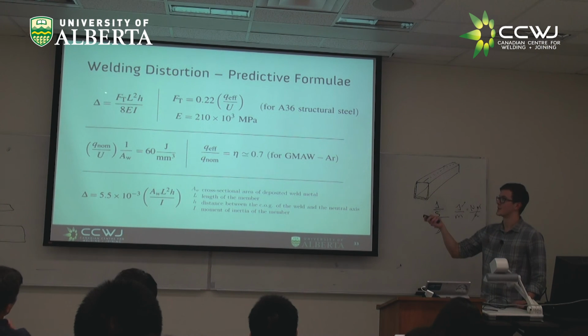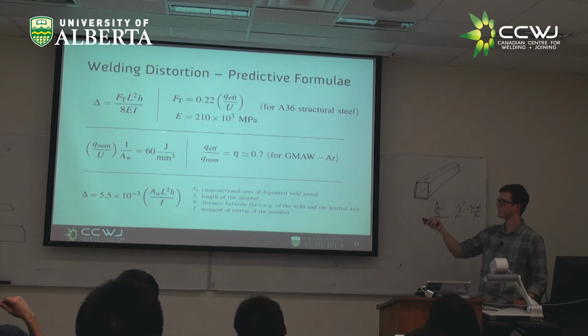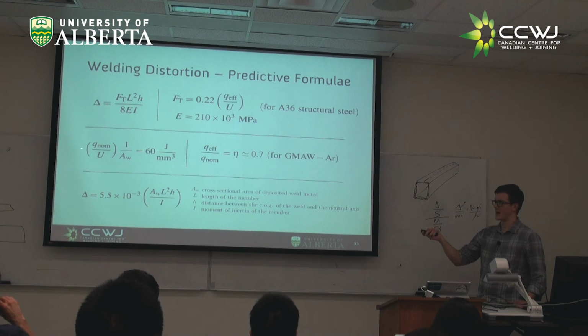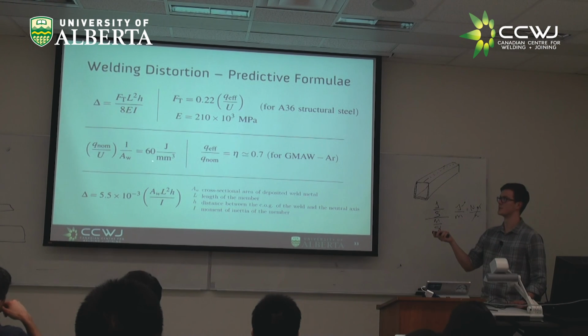So we have this Ft, but we know for structural steel that's about 0.22 times our Q effective over U. And our elastic modulus is about 210 gigapascals, 210 times 10 to the 3 megapascals. Now the other thing they had is a weld area instead of a heat input. We talked about this at the beginning of class, but this came from our lecture on metal deposition. For a given volume of weld deposited, there's an approximate relation to heat input, about 60 joules per millimeter cubed.